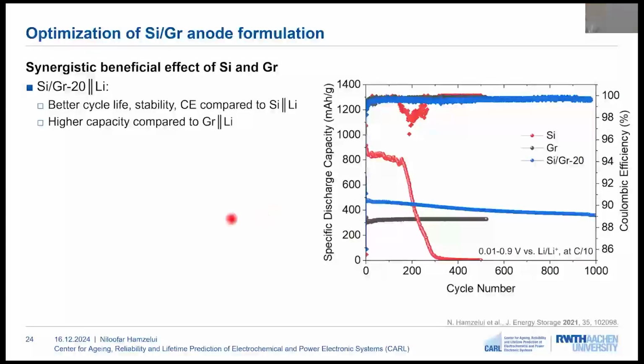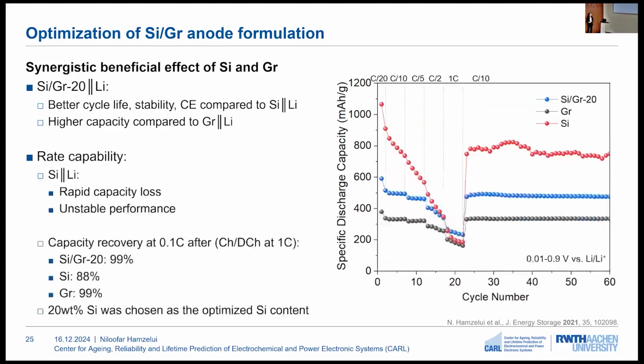Here we can see the electrochemical performance of the silicon graphite composite with 20 weight% silicon, as well as pure silicon and graphite electrodes. And here we can see the synergistic beneficial effect of using a silicon graphite composite, which is an increase in the capacity compared to the graphite electrode, and a better cycling performance compared to the silicon electrode.